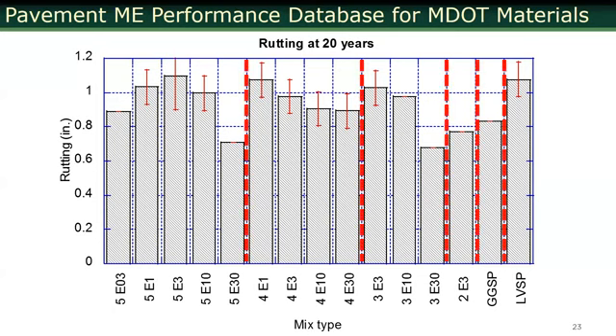But this is an interesting slide, I believe. We analyzed 44 mixes, and we grouped them based on design ESALs, 4E1 through 4E30. What we've seen is for rutting, there's some variability here, but typically as you go higher in traffic level, you get less and less rutting, which is kind of expected. As you go to higher traffic levels for 3E mixes, you get less and less rutting. And for 5E mixes, you get less rutting from 3 to 30 mixes, but we got some unexpected results from 0.3 to 3 mixes. We would be expecting that they would have more rutting than the others.